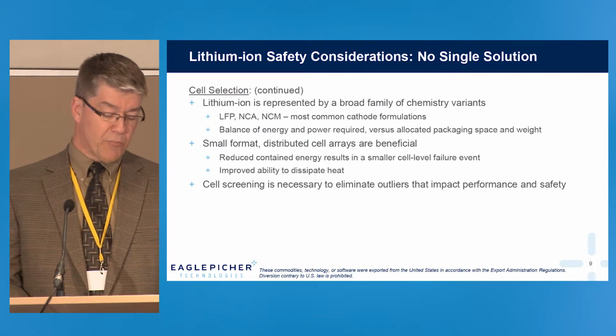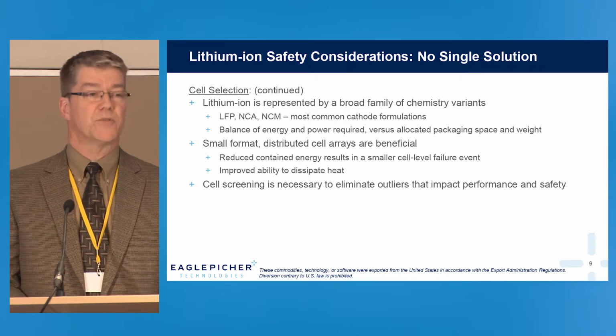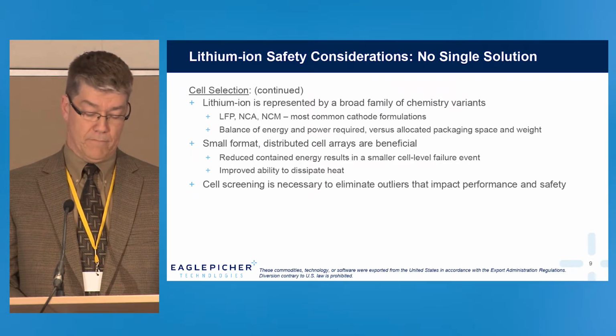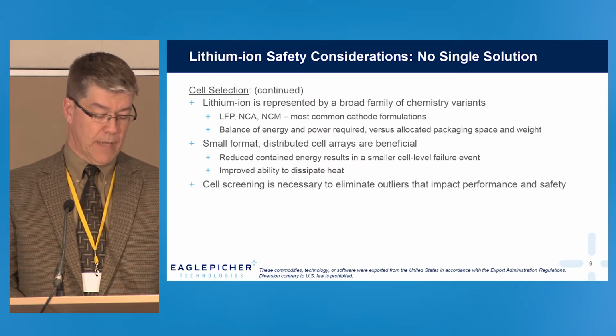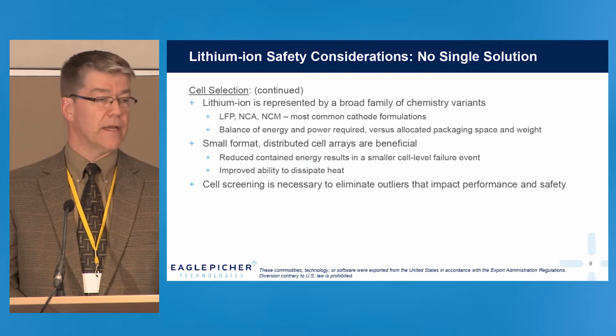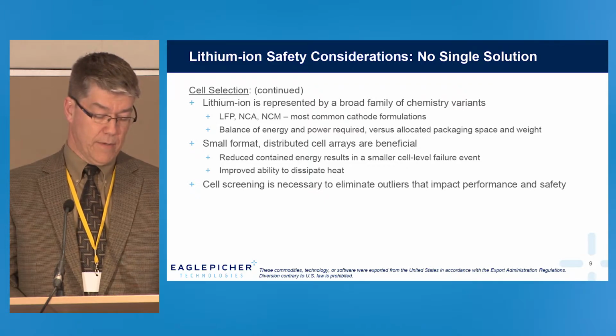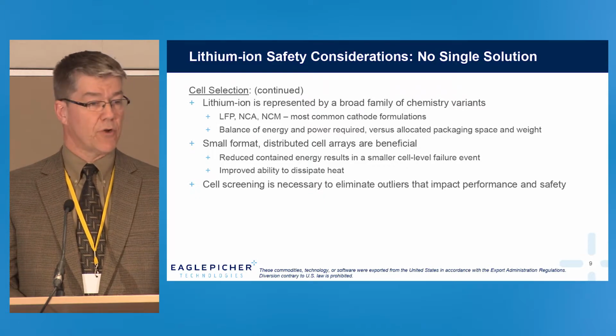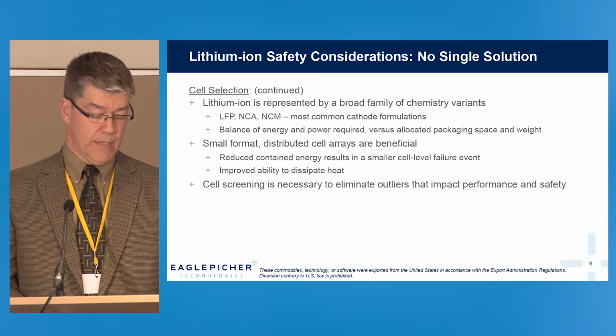So lithium-ion is comprised of a broad family of chemistry variants, mostly differentiated by the cathode composition. LFP, or iron phosphate, is typically a heavy solution, but supports high-rate discharges, relatively low energy. NCA and NCM variants, cobalt-based, typically offer the highest energy densities.